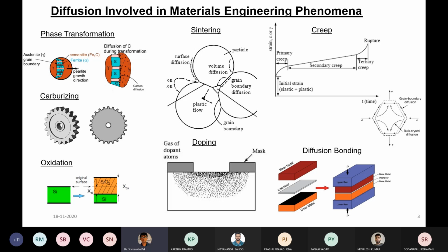Now we are going to understand how diffusion is important with respect to oxidation. Corrosion sometimes is due to certain kinds of reactions, so basically a reaction process is going to take place. In oxidation, if you put silicon in an oxygen atmosphere, then it will oxidize to silicon dioxide. And this oxidation process requires diffusion of oxygen from the surface of that silicon block to the inside, through channels. It can be voids, it can be vacancies. So this kind of movement of oxygen is important. This kinetic factor is important to understand how oxidation of a particular metal is going to happen.